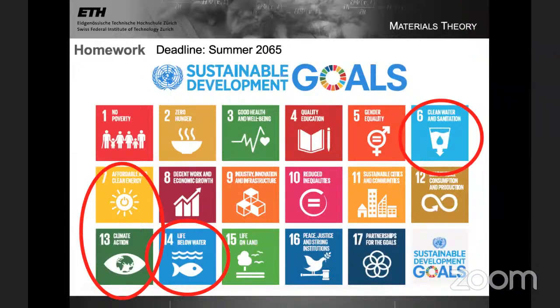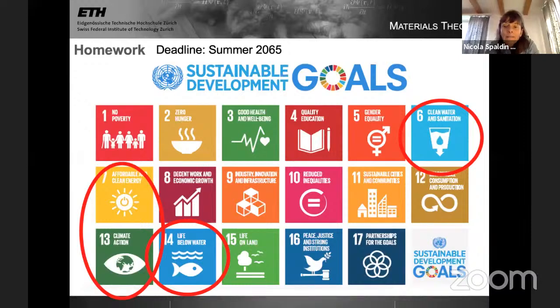How effective is the method of DFT to calculate the multi-properties, for example, the magnetic and the electric properties at the same time? How effective is DFT? Yeah, that's a very good question. Actually, very standard density functional theory does rather well with multiferroics. They're not particularly exotic materials. We know that DFT is very good for electric polarization. There are magnetic insulators where, bismuth ferrite is a d5 ion, so the gap is a huge exchange gap.